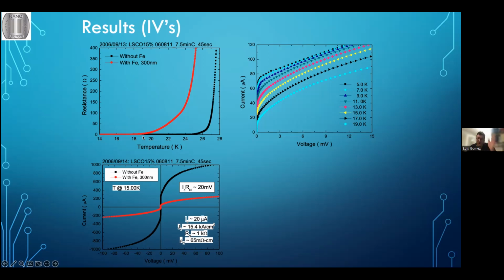So we stop at every value in temperature, and then we do an IV, which is basically we repeat this curve. So this curve at 15 kelvins is this one in yellow with the triangle. This curve would be a blow up of this curve over here. You can see the yellow one goes from 0 to about 30, so it's the 20 microamps. This is in microamps, so the yellow is around there, around the 20.